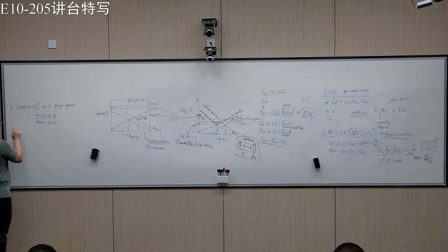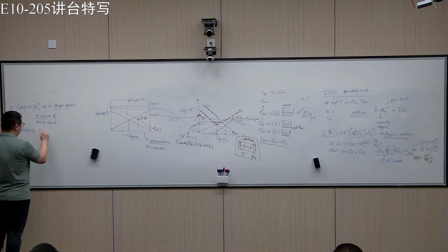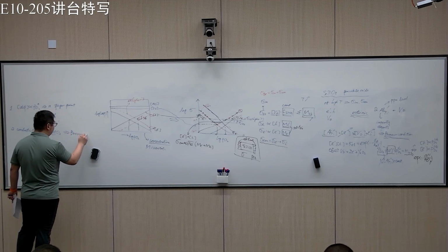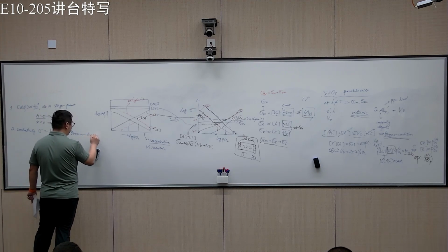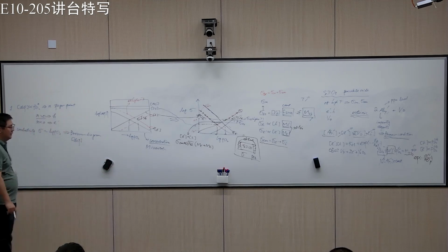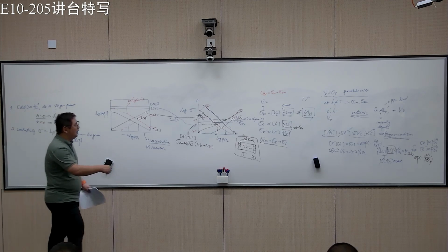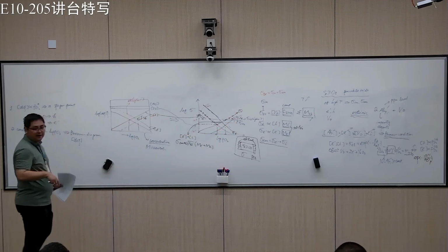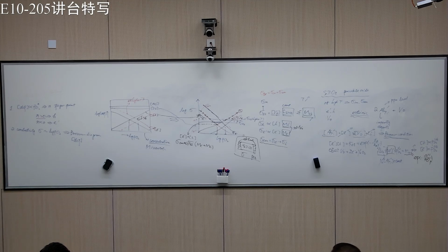Another thing is if you measure conductivity, sigma as a function of log PO2. That actually gives you a way to reconstruct the Brouwer diagram, or at least to know something about defect concentration. If I measure conductivity and I see that it's 1/4, I can guess that it's dominated by holes rather than electrons. So it basically has something to do with defect concentration.